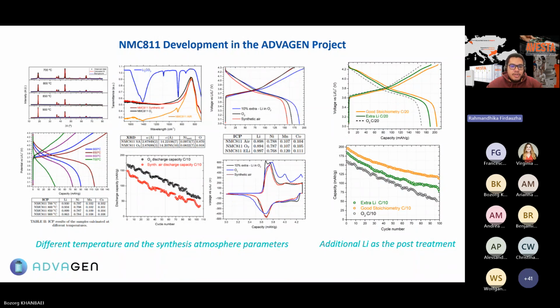And this is the result for the charge discharge when we try different temperatures, where the best one is 850 degrees C, because at that temperature we can maintain the crystallinity of the NMC 811. And then with the atmosphere parameter, we also try several options: synthetic air, oxygen, and air only. By these trials, we can see which kind of atmosphere we can use to optimize the NMC 811 development.